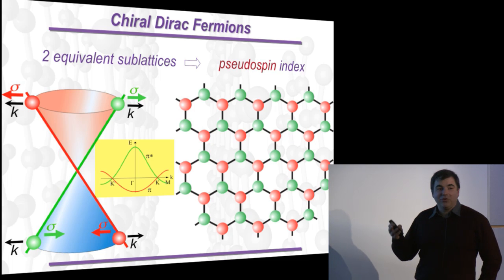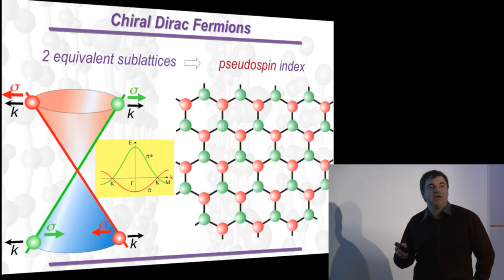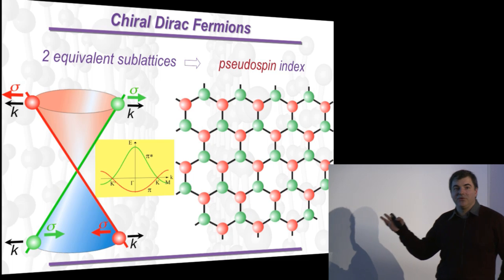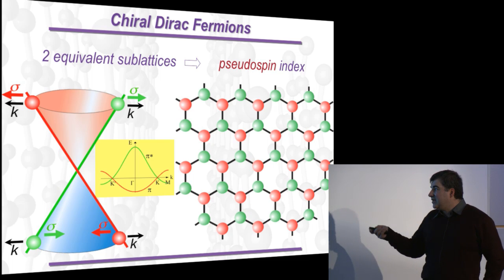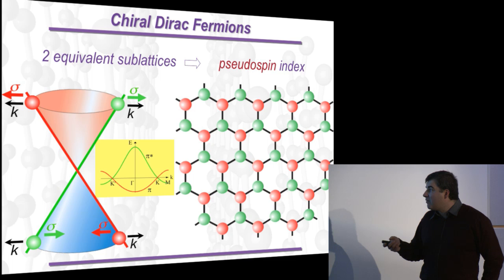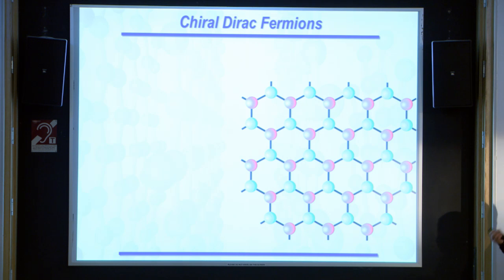So all those properties are really coming from the hexagonal symmetry which we have for carbon atoms in graphene. The hexagonal arrangement of carbon atoms looks extremely simple, but in fact it's not the simplest possible. It's not one of the 6 simple Bravais lattices, because you cannot take one atom and replicate this hexagonal structure. You always need 2. So I colored them differently, the red and the green. Of course, in reality, they are not colored, but you can always distinguish between them.